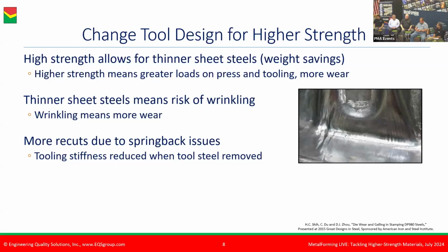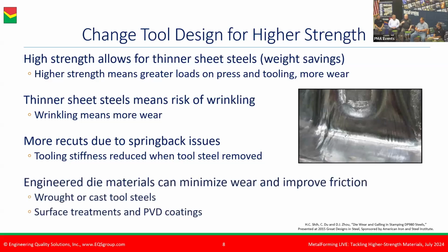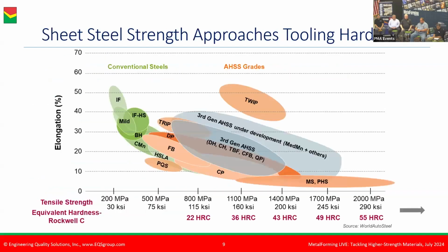And that means you have the risk of tooling recuts when you're trying to do your tooling development to account for that. If we recut these materials so much, we now have the risk of our tool not being sufficiently stiff. So we need to account for that. And the tooling material that we use, we need to upgrade from our older strategy when considering that we're now dealing with higher strength metals, and the products are out there.